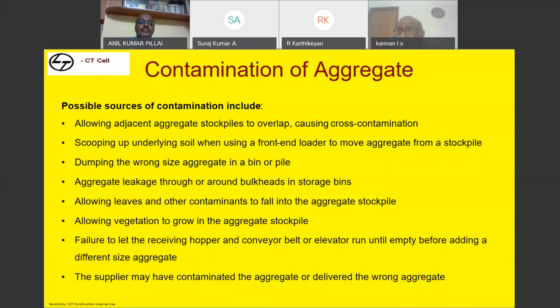So as a user of the material, if you find something, you have to remove the vegetation and the contaminated material, and it should not be used for concrete unless it is washed and processed. Failure to let the receiving hopper or conveyor belt on the elevator run until empty, already I have said. The supplier may have contaminated the aggregate by delivering a wrong aggregate. This also is possible. Your delivery challan will be for some size of aggregate, but what has been delivered is something else. So make it a practice always.